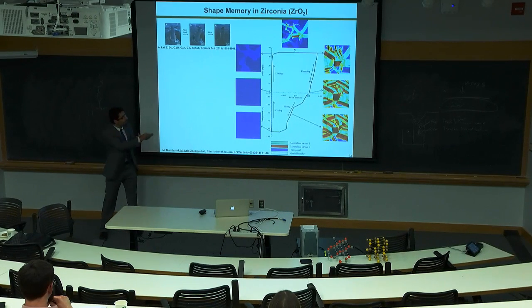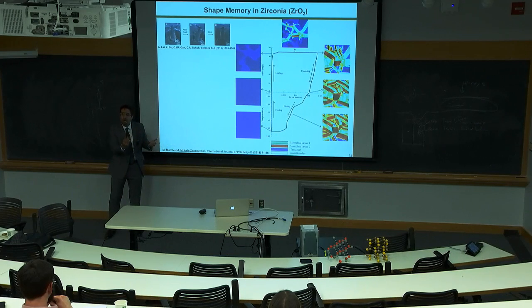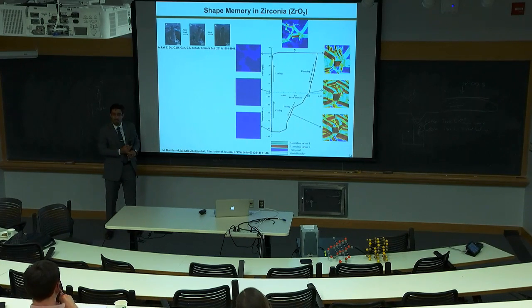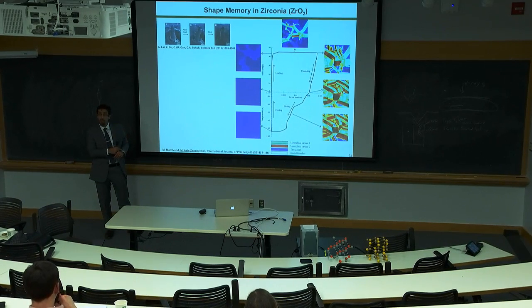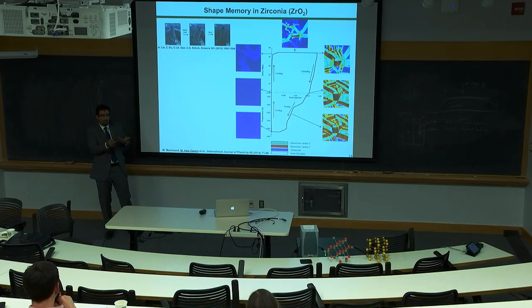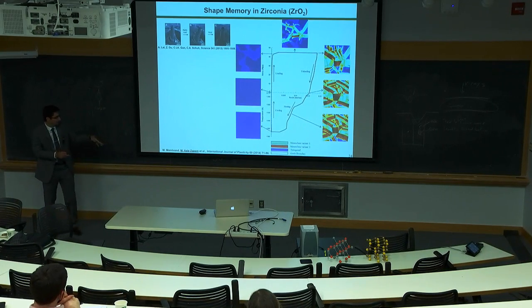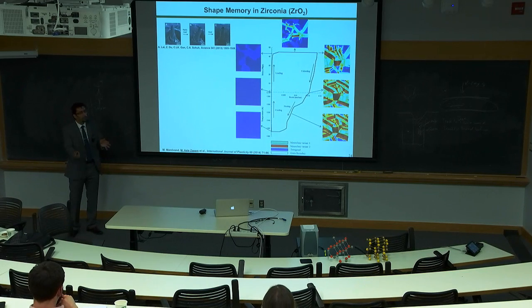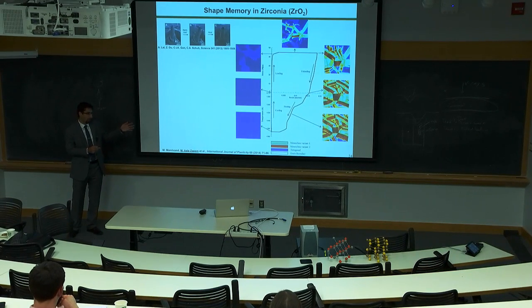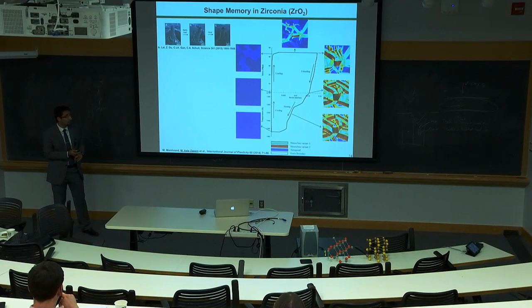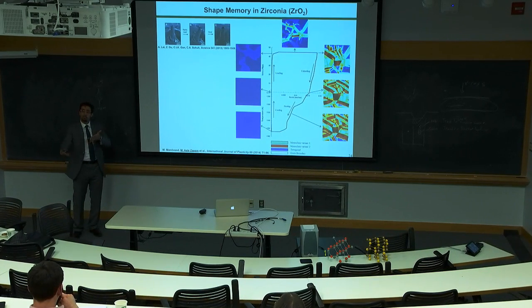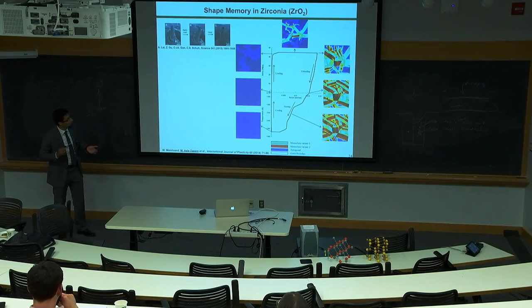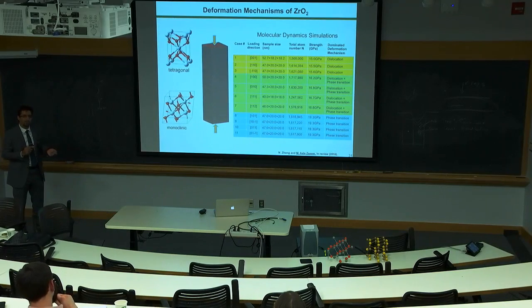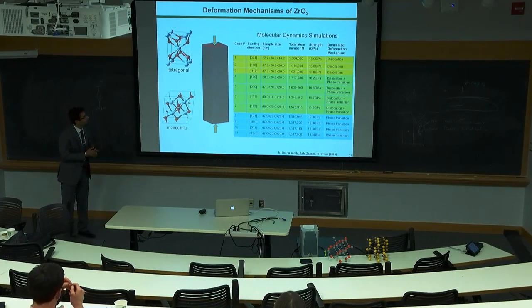So it means if you load and unload, heat and cool 100 times, you get a different path. This is called hysteresis. Do you get a different hysteresis loop? The answer is no, because you don't see any defects or dislocations. So at this moment, actually, it was 2014, I decided that I should go in a different direction. And we did a heavy literature review to see if there was anything on deformation mechanisms or failure mechanisms of zirconia, and there weren't any. So we started a different line of research based on that, just finding something that's important.